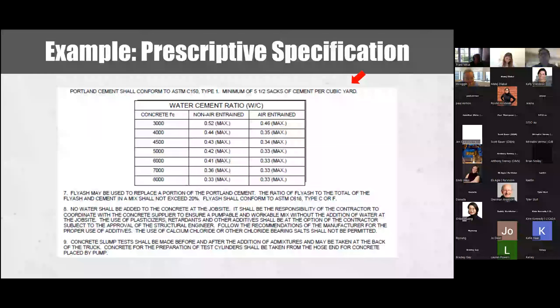It was intended as a conservative start for someone who did not have any basis for establishing the mixture proportions as a start. Clearly, the water to cement ratios stated for typical strengths are significantly low and are not consistent with the strength that will be achieved at that water to cement ratio, and are not consistent with the cold durability requirements. There is a limitation on the amount of fly ash. The intent of this is not clear.